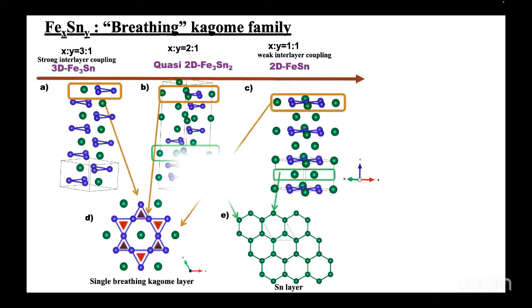So we go from the three-dimensional to the two-dimensional. And when we see from the three-dimensional, we have a strong interlayer coupling of the Kagome family, where you have the Kagome layers, one over each other, which is laterally displaced. And when we reduce to the quasi-2D, we have a Kagome bilayer, which is separated by the hexagonal tin layer. And further going to the two-dimensional, we get an isolated Kagome layer, which is well separated by the tin layers.